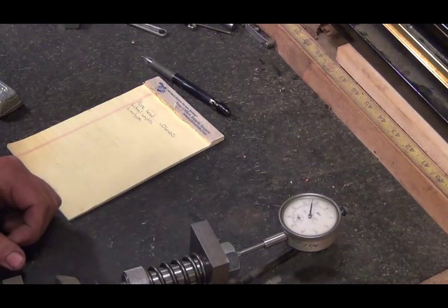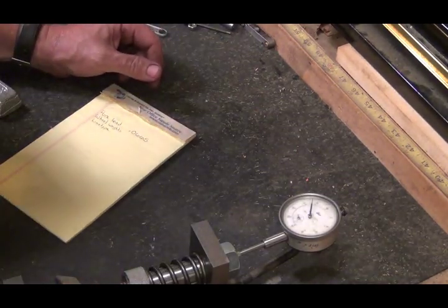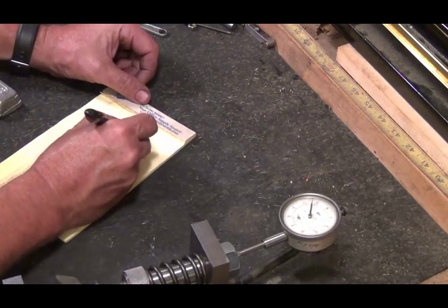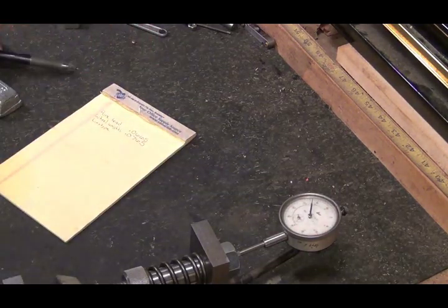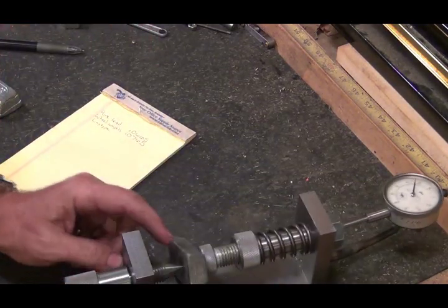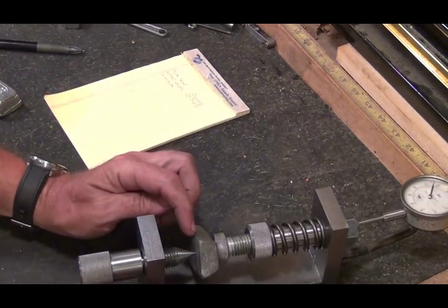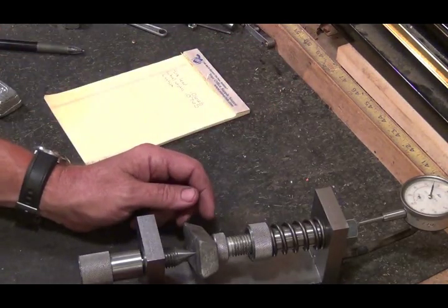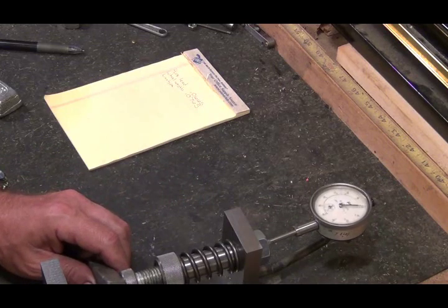The wheel weight came out at 0.0765. The whole idea is that sharp point — the harder the lead is, the less it will penetrate into it, and it'll deflect my indicator more.